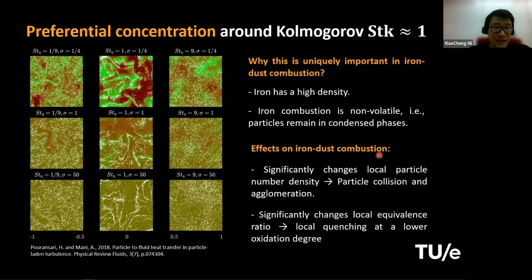And why this is uniquely important for iron combustion, you can see here, they have different simulation pictures, not for iron, but just for some inert particles. When your Stokes number is around unity, you can see the particles are concentrated at some thin regions rather than uniformly distributed over the space. And if your Stokes number is much smaller than 1, it follows the flow field, right? And if Stokes number is much greater than 1, the particles do not follow the flow field, but they do not concentrate on these preferential regions, because they just don't really care about the flow. Their inertia is too large to be easily entrained by the gas flow, right?